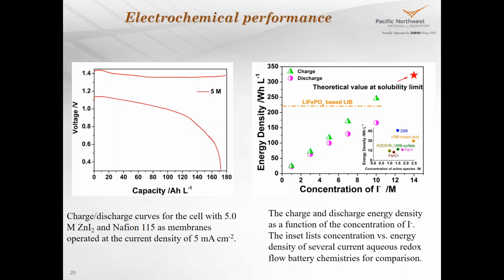So here is showing the charge and discharge of the 5 molar zinc iodide system. And on the right side, you can see the comparison between the energy density of the lithium iron phosphate based lithium ion battery and the zinc iodide battery. So at 5 molar, which is 10 molar of the iodide concentration, the energy density of the zinc iodide approaches that of the lithium ion batteries.